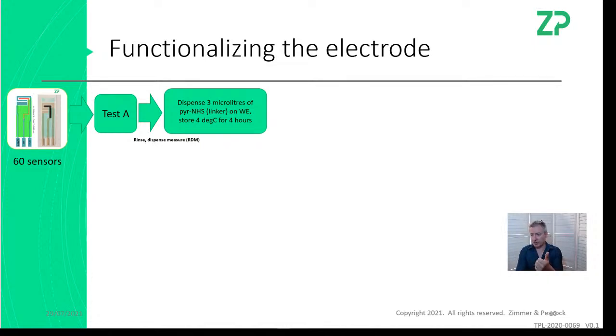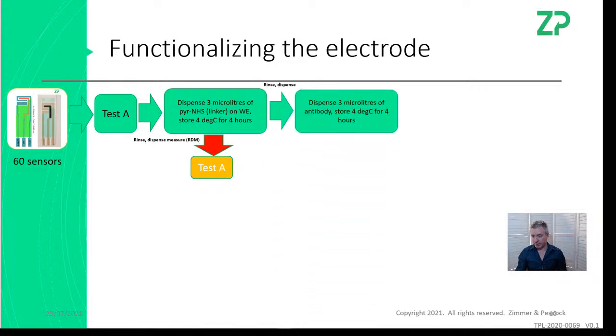So it tells you a few things there. First of all, we've checked the electrodes. We made sure that we think they're good. We've rinsed the electrodes, so we've got rid of all that ferricyanide. We've put the coupling agent on there, and we've left it at 4 degrees for 4 hours. So we've controlled the time and we've controlled the temperature. Then we test them again to make sure that the coupling reagent has essentially bound. And then we test them to make sure that the binding took place. Then we rinse them and we add the antibody and we test them again.